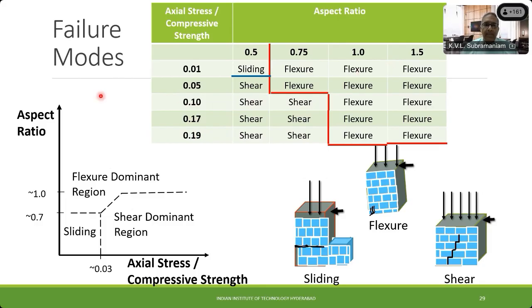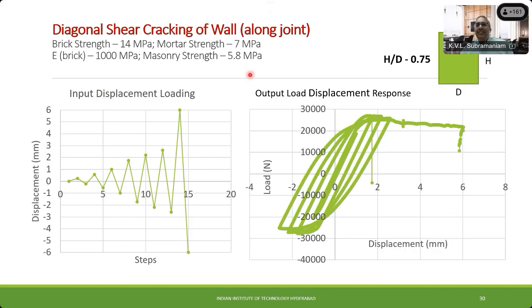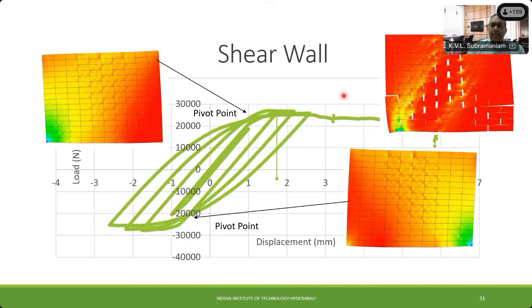Now, after we identified these modes of failure, next thing was to predict the cyclic behavior, where we started looking at the cyclic behavior of this masonry subjected to cyclic ramps, and the predicted responses of, in this case, a squat wall, which failed in shear. And this is a typical response that we got from the cyclic behavior. It's what we call a pivot type of behavior, where you see that most of these load cycles are pivoting at a point. Now, this is something that is predicted, where we are starting to see a pivoting behavior.